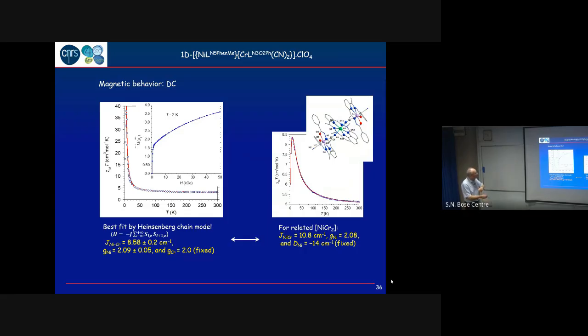But even for that, if it would be antiferromagnetic, what you expect, for a ferromagnetic system, you have something that looks like that, except that at the point it goes down before coming up. The first decrease is a sign of the antiferromagnetic interaction, till the correlation length becomes very large, and then the magnetic moment of your system, even with the antiferromagnetic coupling, becomes large, and the moment is growing. But for a ferrimagnetic chain, you have antiferromagnetic interaction, so it should first decrease before increasing. Whereas here we have a continuous increase, and this is characteristic of ferromagnetic.